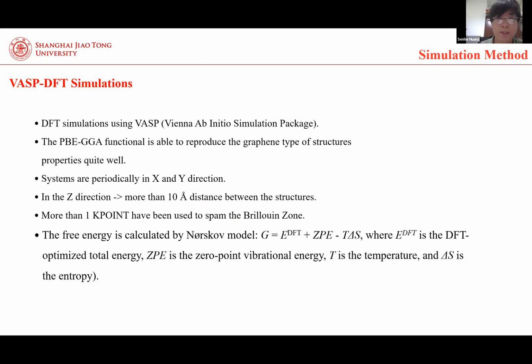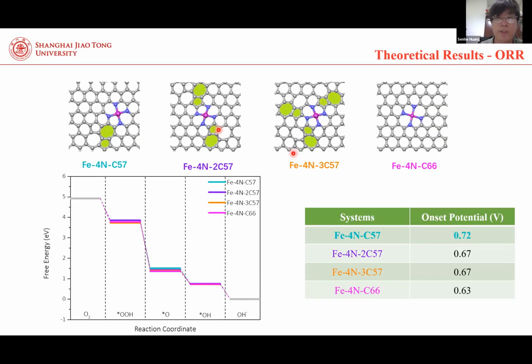Firstly, we investigated the catalytic performance of the catalyst for the oxygen reduction reaction. In the free energy simulation for the oxygen reduction reaction, as shown in this picture, we studied 4 systems. The first system is the graphene system with iron-nitrogen-4 active sites, and this active site is surrounded by only 1 5-7 defect. Similarly, the second system is a graphene system with iron-nitrogen-4 active sites, but it is surrounded by 2 5-7 defects. In the third system, the iron-nitrogen-4 active site is surrounded by 3 5-7 defects. Besides, we also investigated the graphene system without defects.